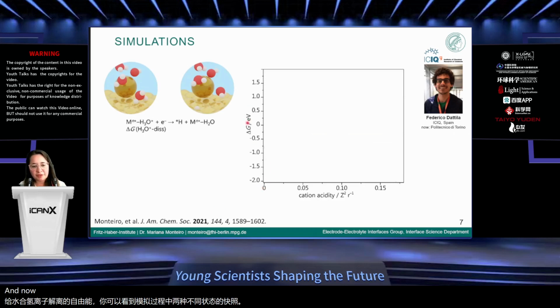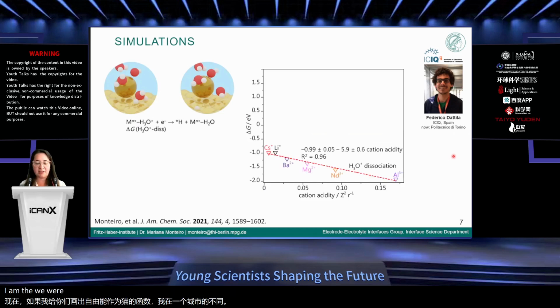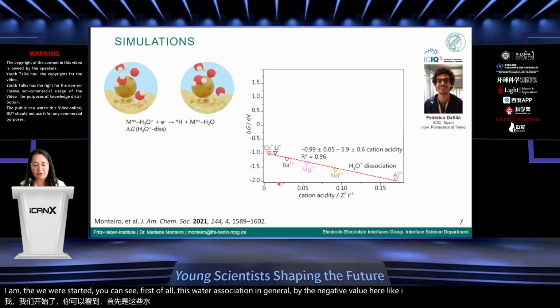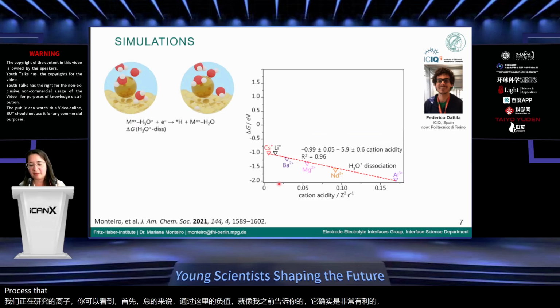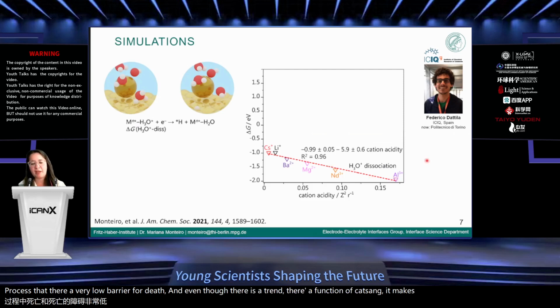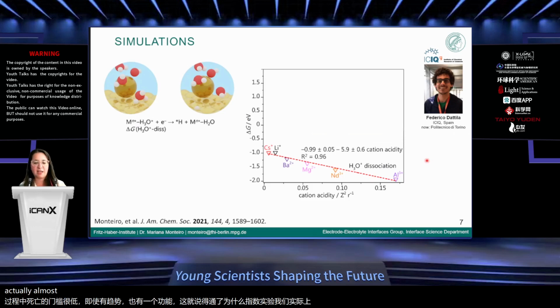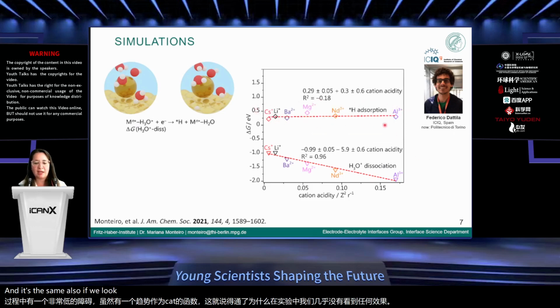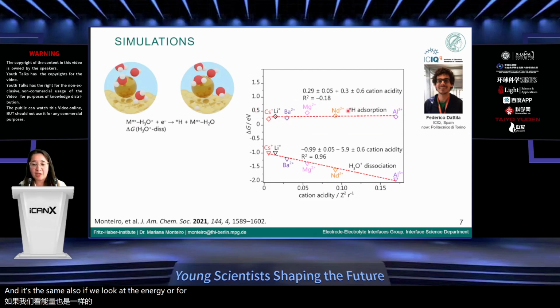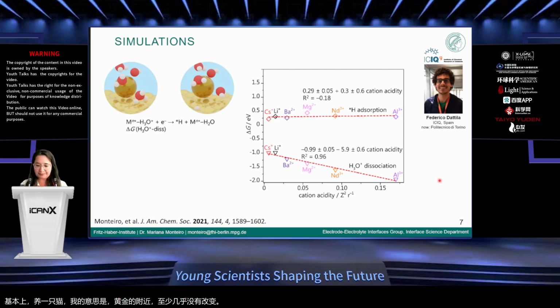Now if I plot for you the Gibbs free energy as a function of cation acidity for the different ions we were studying, you can see, first of all, that water dissociation in general, given the negative values here, is indeed a very favorable process, with a very low barrier. Even though there is a trend as a function of cation, it makes sense why in the experiment we almost don't see an effect. It's the same if we look at the energy for an adsorbed hydrogen on the surface: having a cation in the vicinity on gold almost does not change that, which nicely agrees with the trends we saw in the voltammetry.